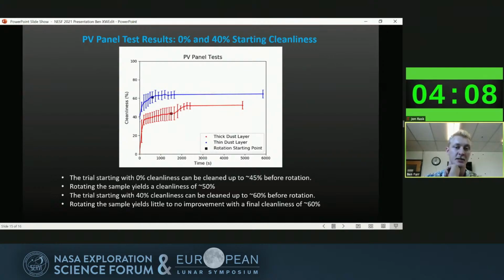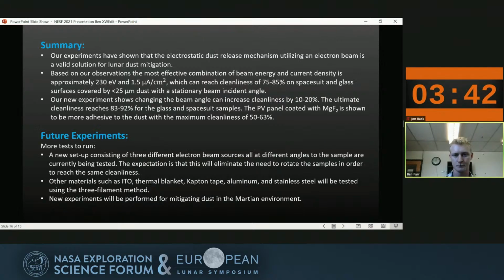And then we also tested a photovoltaic solar panel with this rotation method, and that wasn't quite as good. So we found that for a thick layer, we get about a 10% increase, from maybe 45 to 55%. But then for a thin layer, we don't really see too much change at all. And that's just because the actual solar panel is very, very adhesive to the dust, and we have yet to discover why. That's something for the future.